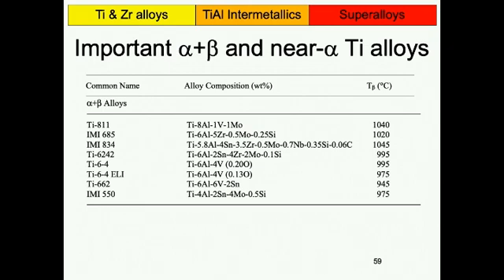So you can see the silicon, which I mentioned. There's actually a tiny amount of carbon. I don't really know what the purpose of this is. A tiny amount of niobium, which is a beta stabilizer. Molybdenum. Now, actually, I haven't really pointed that out. That the modern near alpha titanium alloys, they've replaced vanadium with molybdenum. And the reason for this is molybdenum is a much more slowly diffusing element than vanadium. So molybdenum is a slow diffusing element. It's a beta stabilizer, but it has very slow diffusion rates. And for high temperature application, that's very beneficial. But it's the molybdenum which makes it quite tricky to process the material as well.